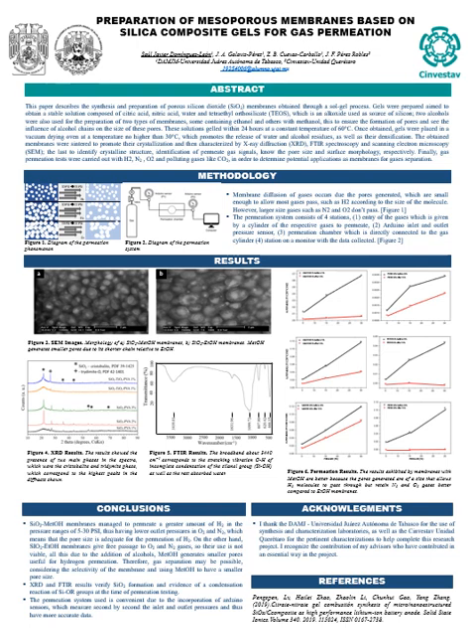Silicon dioxide and methanol membranes manage to permit a greater amount of hydrogen in the pressure range of 5 to 30 psi, while lowering the passage of oxygen and nitrogen, which means that the pore size is adequate for the permeation of hydrogen. On the other hand, silicon dioxide and ethanol membranes give free passage to the oxygen and nitrogen gases, so their use is not viable. All this is due to the addition of alcohols.